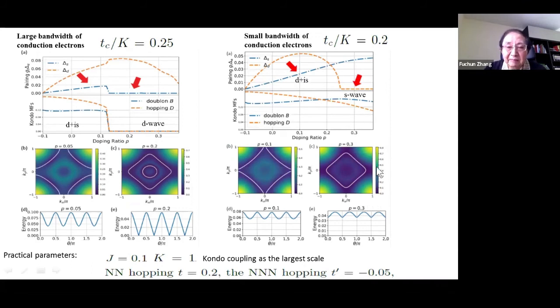At the right side panel, what I show you here is where the Kondo totally dominates. Okay, so it means a small bandwidth of the conduction electron. Actually, in the competition here, S wave wins at large doping. Okay. I think experimentally probably more relevant is this regime. Okay, so the main point of this t-J-Kondo model is that the pairing symmetry changes when you dope, okay, from like a D plus iS to a D wave pairing. When I say D wave pairing, I mean that probably is similar to cuprate, okay, but at the light doping situation it can be quite different.